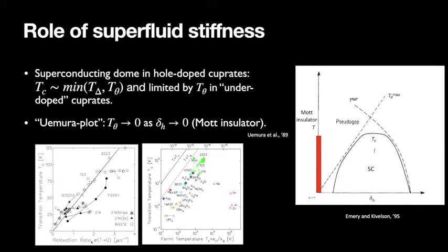So I don't want to go into the details of how this phase stiffness was measured, but empirically there is a linear relationship. Okay, and then from here on, this behavior has been seen across many different systems, and so this is why anytime a new sort of strongly correlated superconductor is discovered, people often try to put it on this plot, where you see TC versus TF, because naively, if one doesn't think too deeply about it, and this is something I'm going to come back to later, this quantity, the 0 temperature superfluid stiffness, is related to the Fermi temperature.